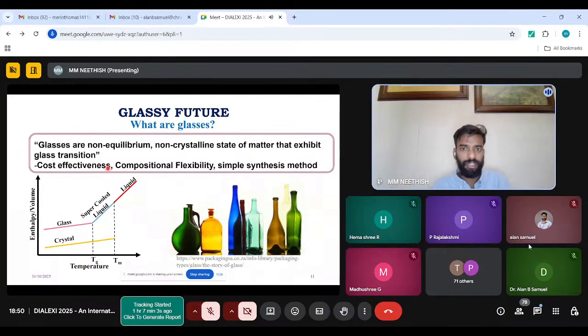So this compositional flexibility is something which crystals do not have, because crystals are a very ordered arrangement. They cannot form in any kind of structure. They can form in a particular structure. So it's not easy to make a crystal of any compositional form. But for glasses, ideally you can make it. And also, to some extent, by adding glass formers or something like that, you can make it up with the composition you want. So in this way, you can tune the material with this composition. You can decide what kind of material you want by slightly tuning the material, which in crystals you don't have this flexibility, because sometimes there are some forms of crystals which cannot be formed.